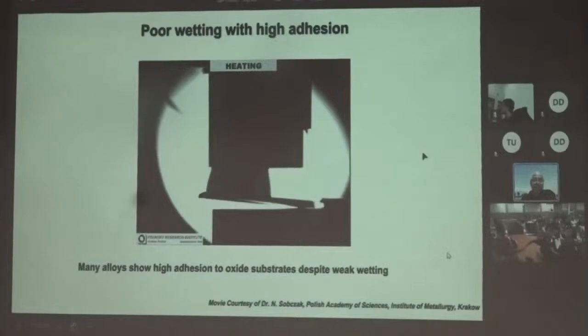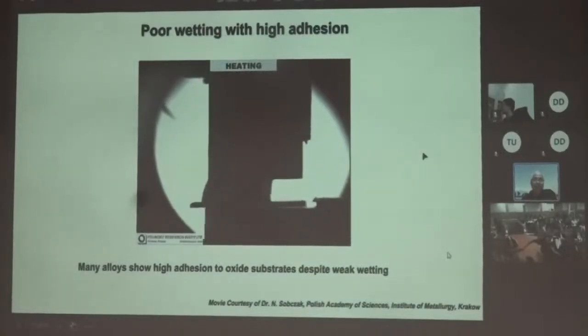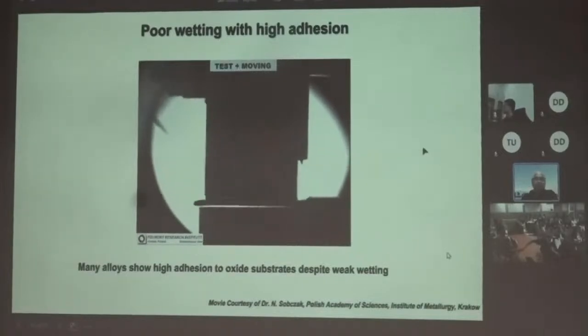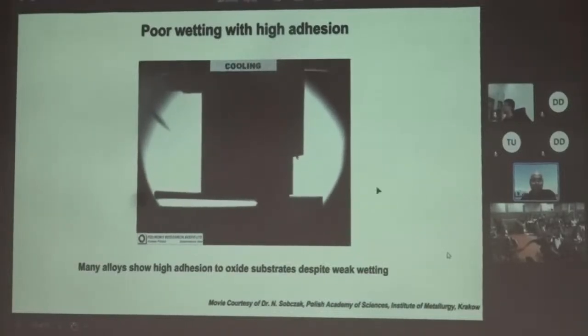Generally, we believe that you need high bond strength, and you need good wettability for high bonding, but that's not always the case. You can see here that this little ceramic plate gets bonded even though the contact angle measured was pretty high.